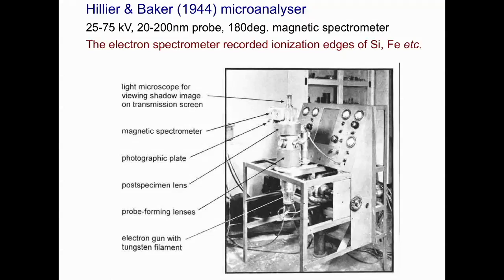The original aim was to analyze with 20 nanometer spatial resolution, and this failed because of the poor vacuum and the resulting hydrocarbon contamination by the electron beam, a problem not that uncommon even today. But by defocusing the probe to 200 nanometers, Hillier and Baker were able to record ionization edges from various elements and to show the distribution of these elements within the thin specimen.